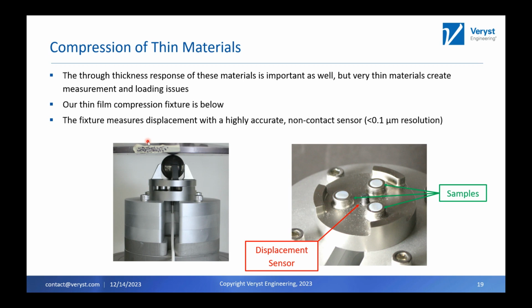Again, this is done on that same electromechanical load frame that I showed earlier. These are the normal compression platens that we would use, and then we apply the displacement. For that displacement sensor, depending on which one we use, and a couple things that go into the math, we have less than 0.1 micron, down to 0.02 microns of displacement resolution. Another thing we really like about the sensor is we can use the same thing at a meter per second, and there's no lag. It's a high frequency response sensor. So it's very accurate, and very fun for us to use.